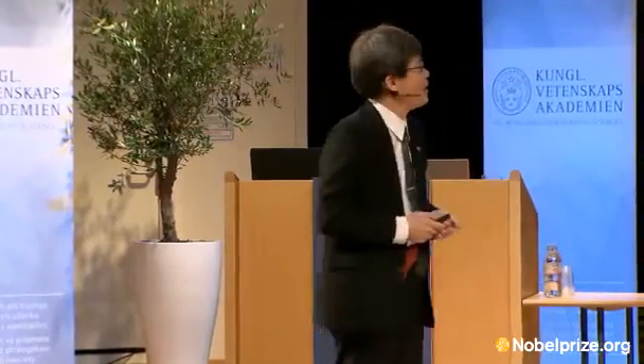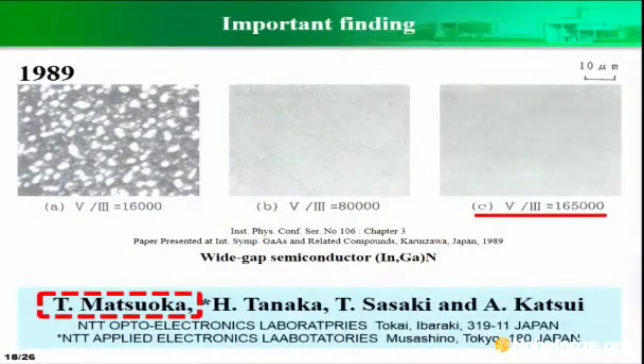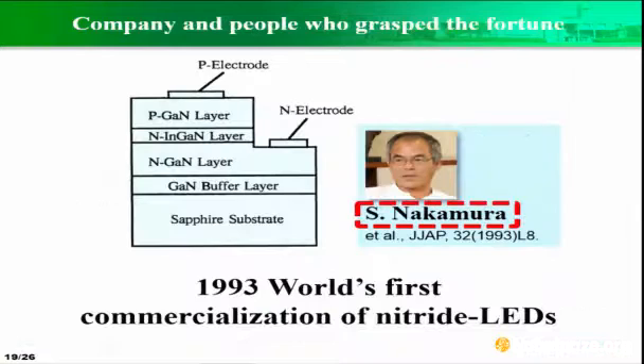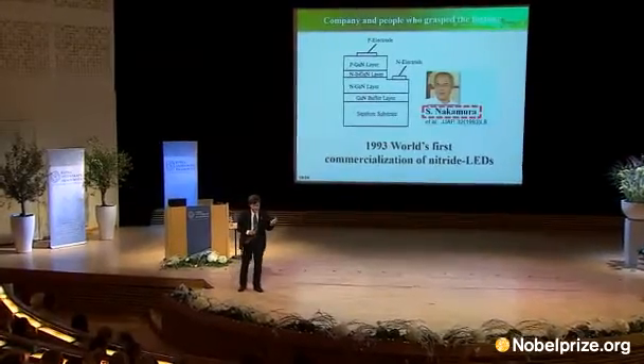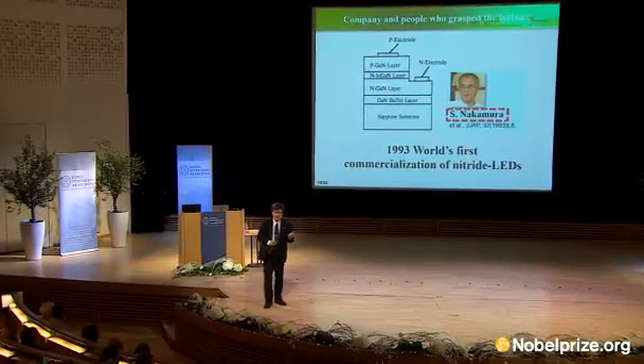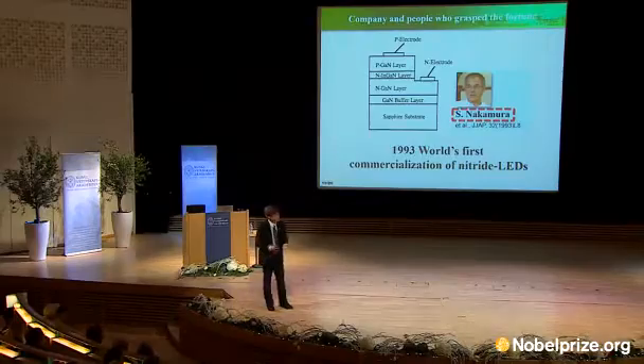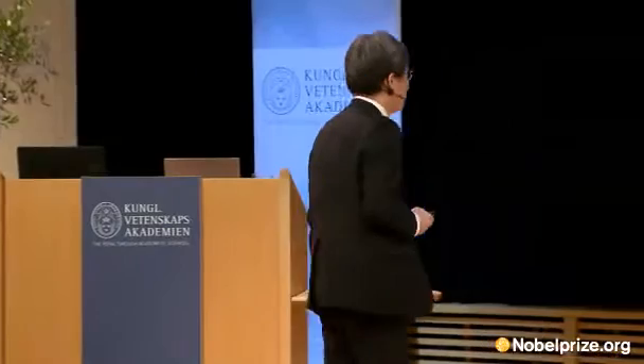In 1989, Dr. Matsuoka of NTT succeeded in growing blue-luminescent indium gallium nitride by growing it under very high ammonia flow rate conditions and in a nitrogen carrier gas atmosphere. So combining the high-quality crystal technology, p-type gallium nitride technology, and the double heterostructure of indium gallium nitride and gallium nitride, Professor Nakamura's team first succeeded in the commercialization of nitride-based blue LEDs in 1993. His group also realized the quantum well-based structure in 1995, which is also very important for improving the efficiency of LEDs. Maybe he will explain in the next presentation.